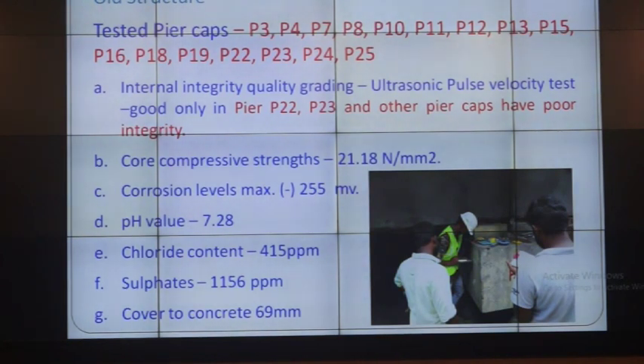Then again some more details of almost similar nature in some more places. 21 instead of 18, now you got the 21 here, same structure, either this or that. The pH value is about 7.28, earlier the 7 point something was there. Chloride content here 415, manageable, okay, it is just in the so-so. The cover is very good, extremely good. Sulfates also very good.